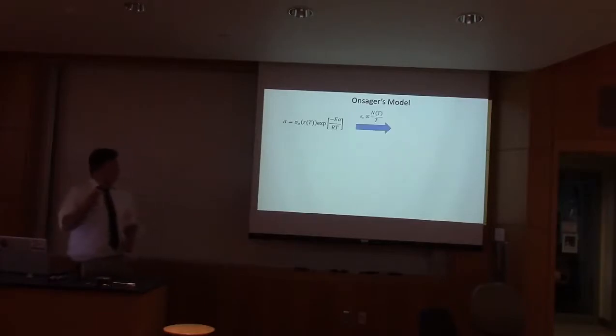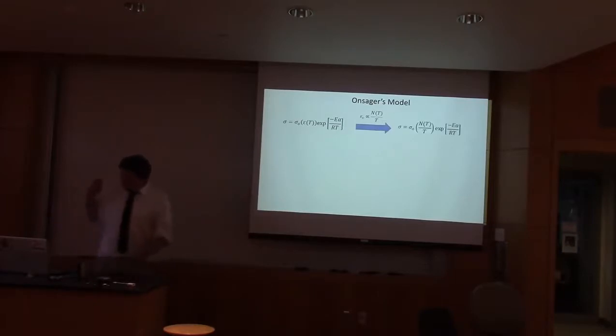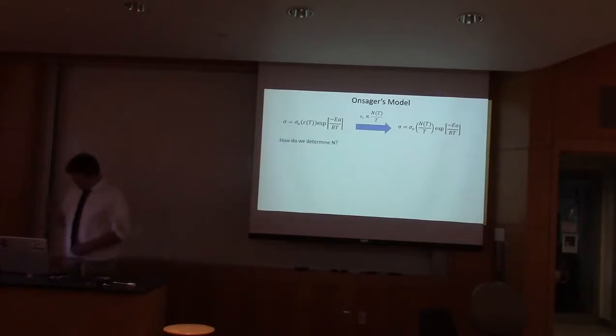Now we can take our original compensated Arrhenius formalism, where the exponential prefactor depends on the temperature dependence of the dielectric constant, and, using Onsager's model, turn it into a new version of the compensated Arrhenius formula where the exponential prefactor depends on the dipole density divided by the temperature.